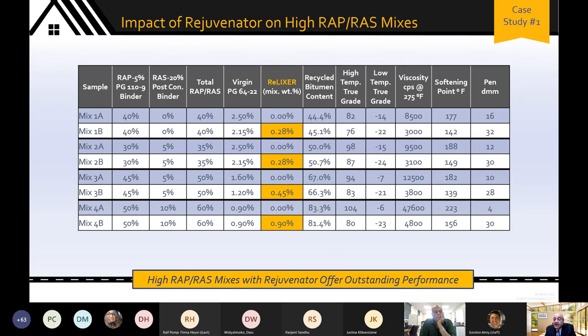What is the impact on properties? Extracted bitumen data, you can see that the viscosity from an almost chewing gum-like 48,000 is now reduced by 90%, more in line with typical elastomeric modified bitumens that you are able to compact in the field. Look at the low temperature grade. Again, it's taking a very stiff material and getting it to almost better than a minus 22. Again, quite commonly used. Look at the penetration. From an almost zero pen material, you're increasing the softness to about a 30 plus pen, which again is in line with what you are using currently for your paving operations. This is what rejuvenation does from a property standpoint.